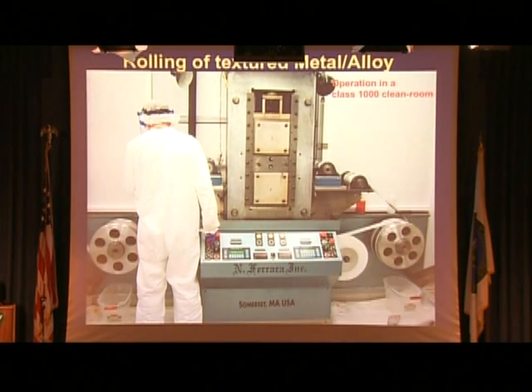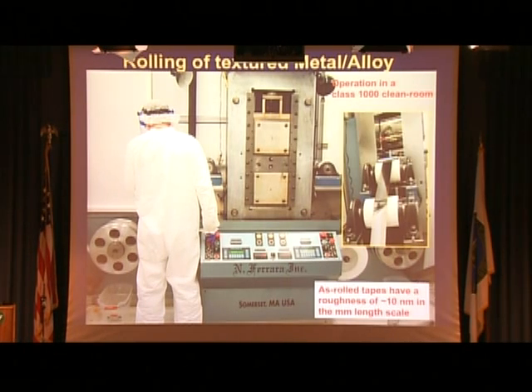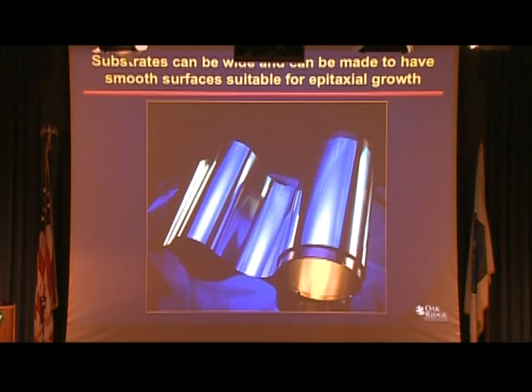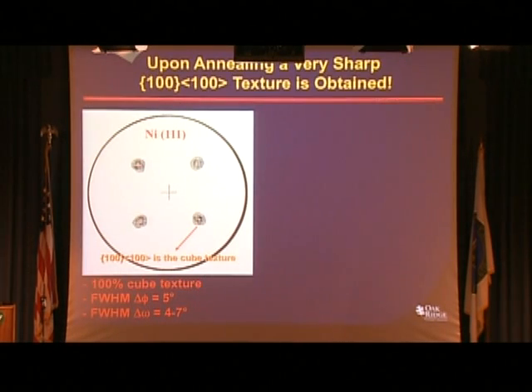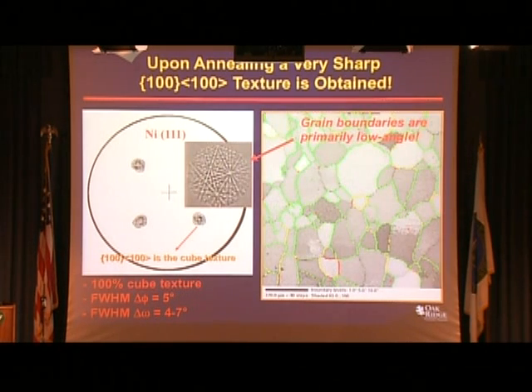The process starts in a rolling mill, in a class 1000 clean room, and the roll tapes are such that they're amenable for thin film heteroepitaxial growth. They can be made, much like aluminum foil, in wide widths. As I mentioned, when you look at the orientations, you have 4 peaks which repeat itself because of cubic symmetry, but the width here corresponds to saying that in a very large tape, all the grains are aligned within 5 degrees.